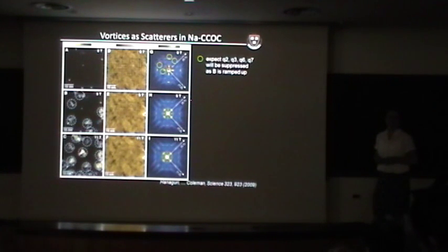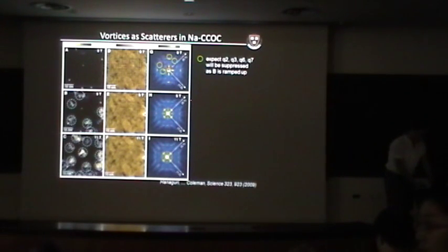I thought the vortex was treated as a tau 1 scatterer, because it's the change of the order parameter which really scatters the quasi-particles. It's magnetic in the sense that the number scales with the magnetic field, but its primary role is to scatter quasi-particles through the variation of delta. But then coherence length has to be an essential parameter, unless it's a phase that you take into account. While one can look at it as a phase winding, then it's okay to consider it a point. If we're talking about the suppression of the order parameter, then there is a length scale associated with this gradient.